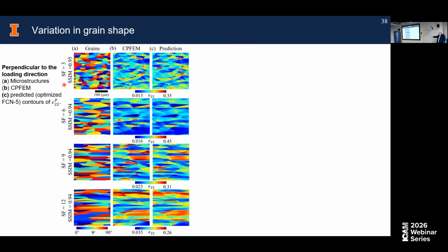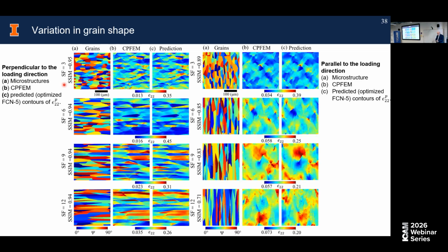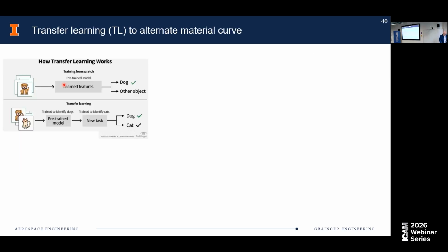Can you play with the microstructure, right? So we created these microstructures that were sort of more additively manufactured type microstructures. It works pretty well when they're horizontal to the load. It doesn't work as well when they're vertical, right? And I think the reason for that is because you end up having certain grains that carry most of the load and the other ones don't do anything, and you cannot pick that up. Again, let me skip through that.